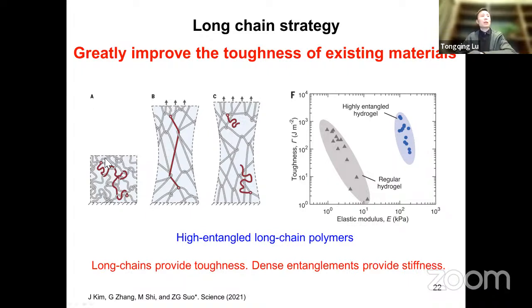So when you design an elastomer, of course, we want to use a very long chain, and also we entangle it. The long chain will provide toughness, and the entanglement will provide the stiffness. So it also resolves this toughness and stiffness conflict. With this design, we can see this highly entangled hydrogel with similar toughness but much higher modulus, or stiffness. So it's a similar idea to use the long chain strategy.